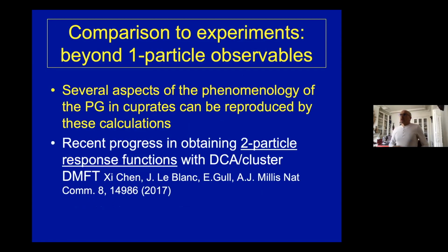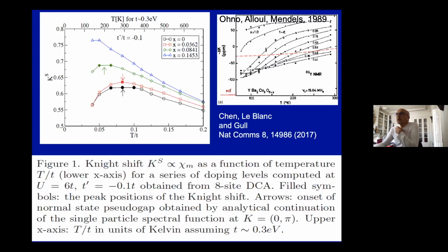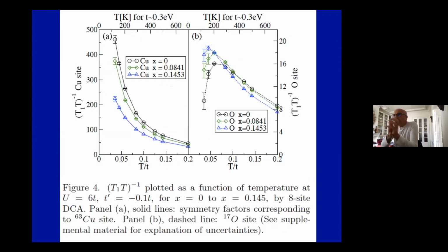Okay, so one can actually, thanks to the calculation of also two-particle response functions, make pretty good comparisons to experiments on cuprates. These are some work by Emanuel Gull and co-workers for the Knight shift and for the NMR relaxation rates that are very similar to what is observed experimentally in the hole-doped regime of cuprates.